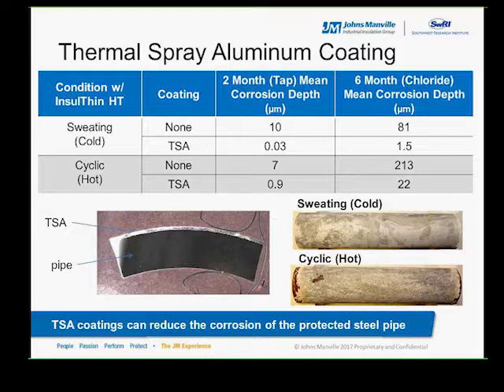The table shown in this slide is split to show the results of both environmental conditions, both the cold sweating and the hot cyclic. Also shown in the table is a comparison between the mean corrosion depth with and without the TSA coating after both the 2-month exposure to tap water and the 6-month exposure to 15 ppm chloride. In all conditions, you can see that the TSA decreases the mean corrosion depth by at least an order of magnitude, and this isn't really surprising since that is what the TSA is supposed to do, but it's also an example of how this test method can be used to explore the impact of not only insulations that we've done earlier in the study, but also the coatings in the full insulation systems.